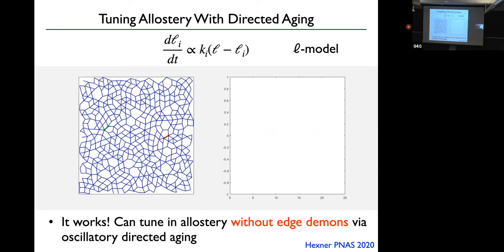So what Daniel did was, here's my source bond. Okay, here's my target bond. And I'm going to just go like this, or I think he did the opposite, which I have trouble with. I'm such a klutz. Okay, but so you're driving both the source and the target with the desired response. And then we're adjusting the equilibrium lengths to lower that elastic energy.